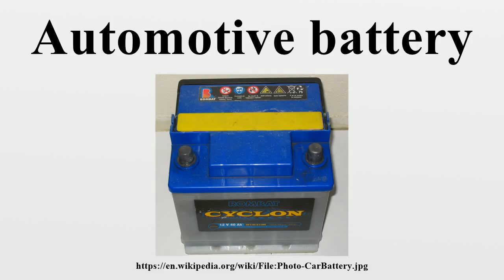Sulfation occurs when a battery is not fully charged. The longer it remains in a discharged state, the harder it is to reverse sulfation. This may be overcome with slow, low-current charging. Sulfation is the formation of large, non-conductive lead sulfate crystals on the plates. Lead sulfate formation is part of each cycle, but in the discharged condition, the crystals become hard and block passage of current through the electrolyte.